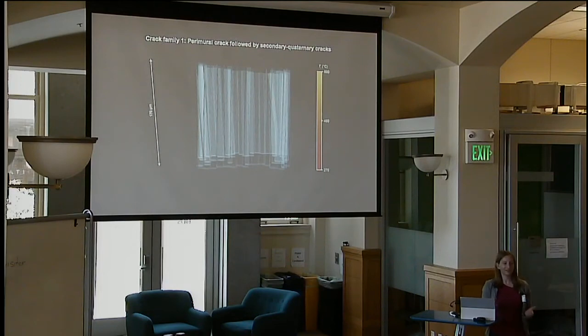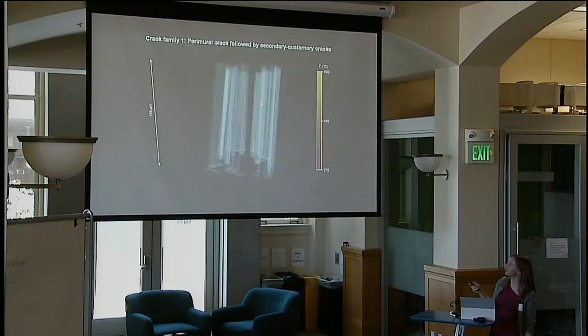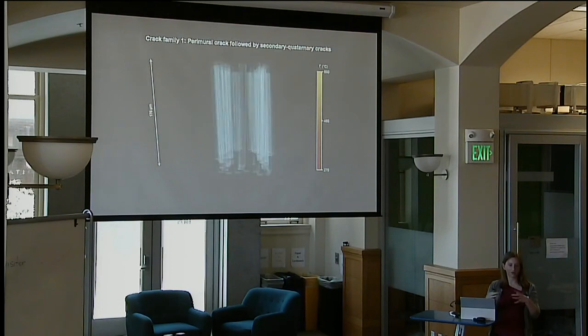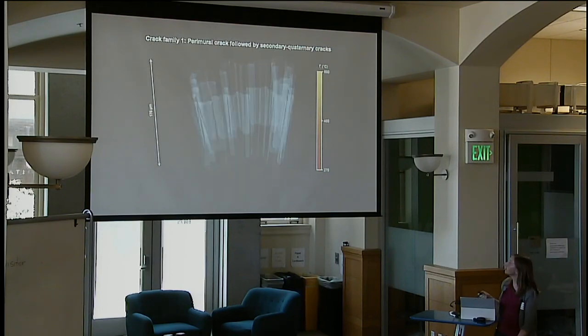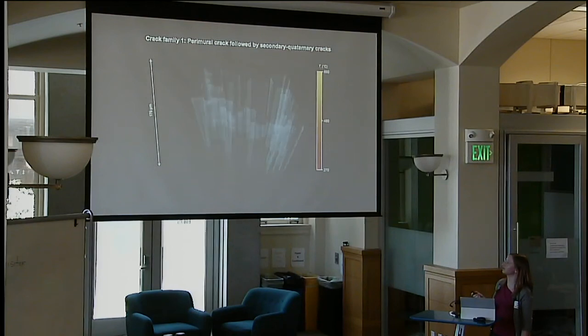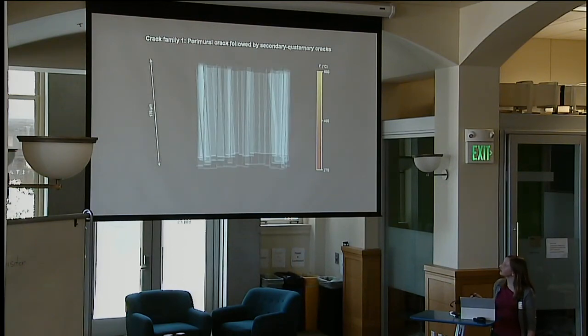Okay, so our first finding is that primary cracks, and these are the first cracks to form in any given region of matrix, fall into two different categories. So the first type of primary crack is what I've called a perimural crack, and I'll show you that in this video, which will show cracks forming over time, and the cracks are colored by the temperature at which they form. So first, to orient you, these blue cylinders are all of the fibers surrounding this region of matrix. This is a relatively large region between the fibers. So then the first crack to form is what I've called a perimural crack.